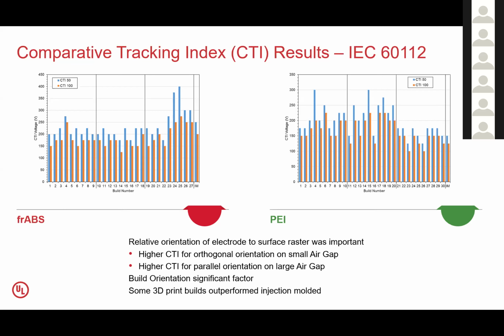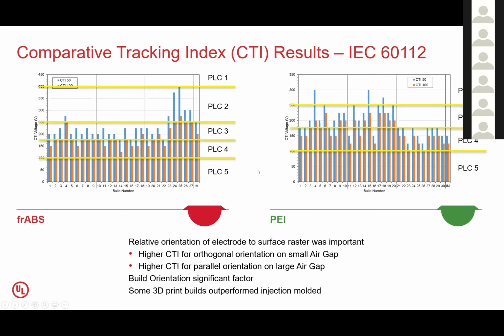We do see that build orientation is a significant factor, as I mentioned. And now it's starting to look like some of our 3D printed samples are outperforming the injection molded. And this becomes important when we consider where materials with these types of results can be used. Materials getting a performance level category of 4 can be used in an indoor application. A performance level category of 3, where we're now starting to see some of these Z orientation builds and the horizontal builds on the polyether imide, is now starting to get into the outdoor, less severe use. And performance level category 2, which we do have in both cases, now you're getting into some severe applications of the material in an outdoor use. So now it becomes very important how the measurements are being done in order to reflect what the properties of this material truly are, to assess the hazard that we're trying to address.